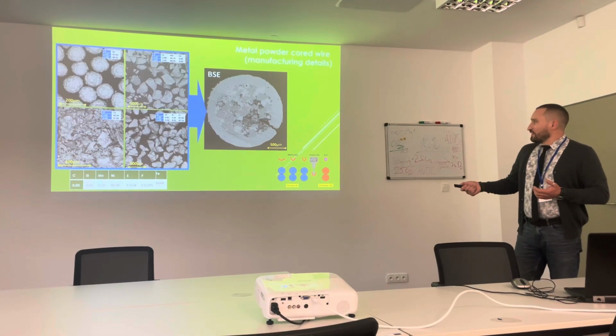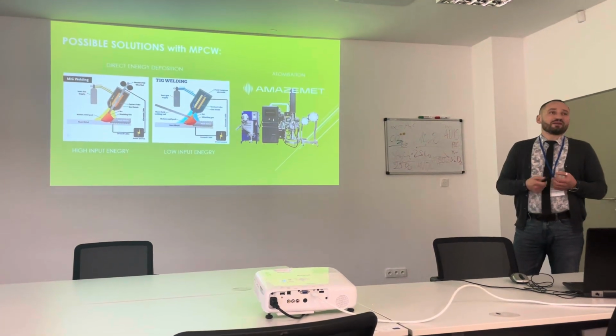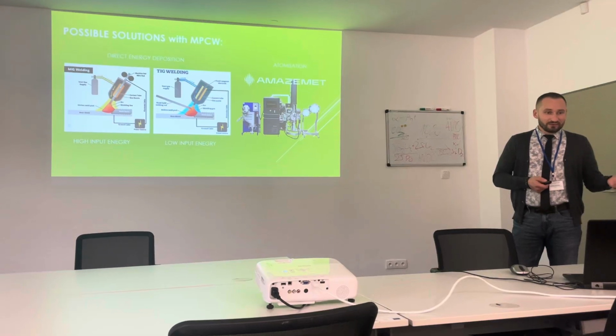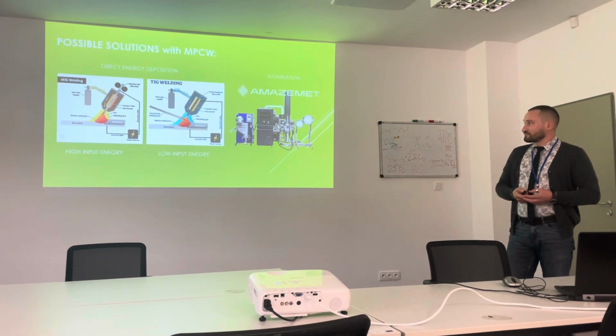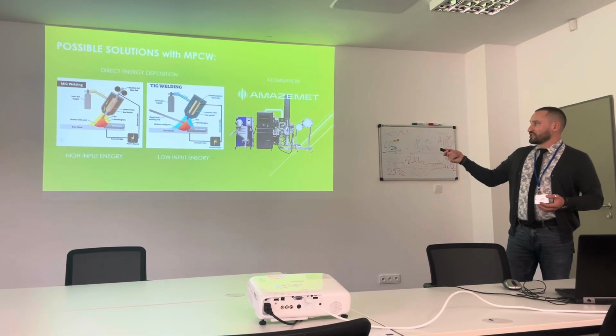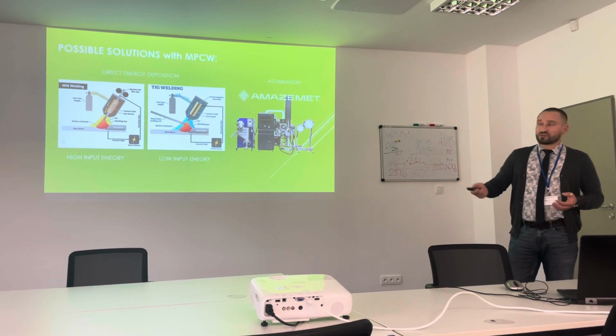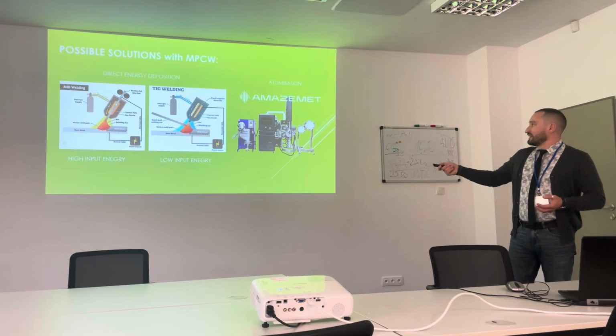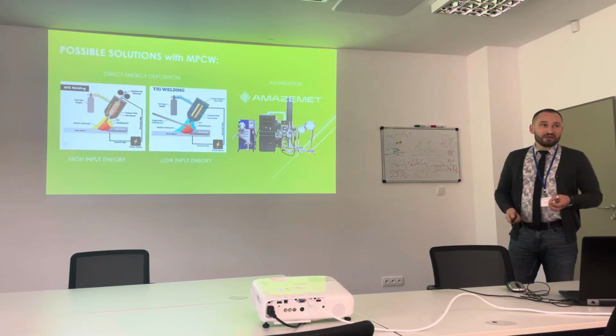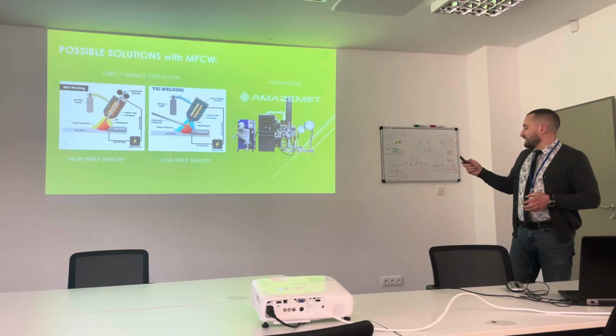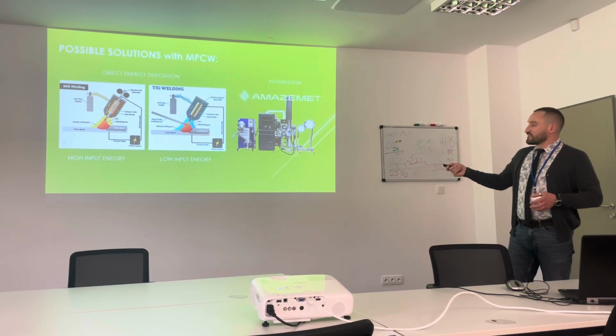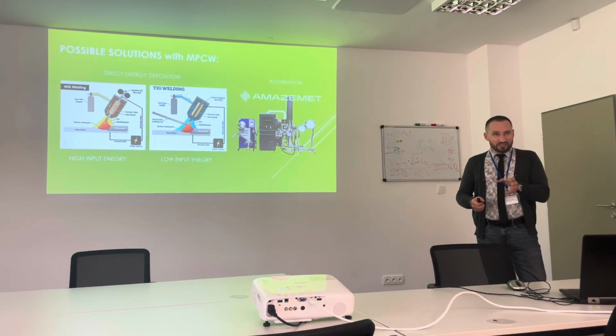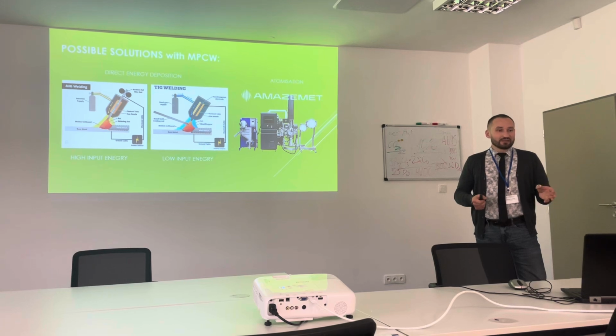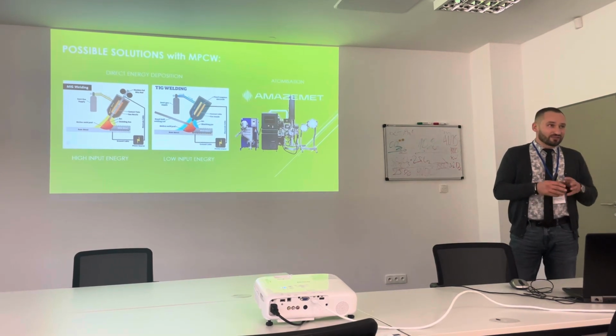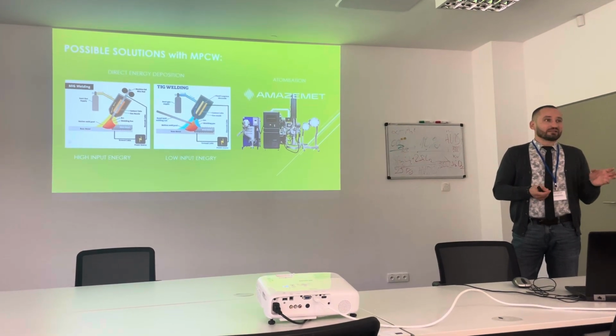Further, we use this filament in a direct energy deposition system. We can use MIG and MAG welding or TIG welding, or another application where we can use atomization. It means that from this metal powder cored wire we can directly obtain spherical particles of high entropy alloy composition.